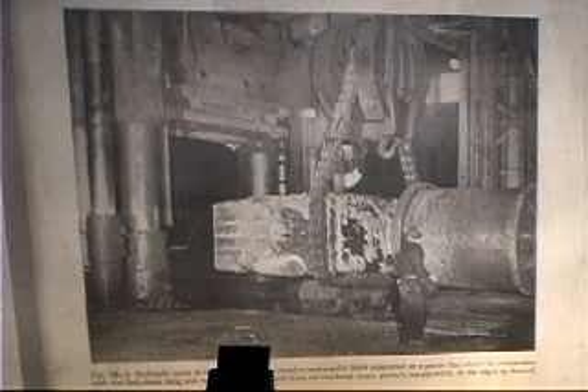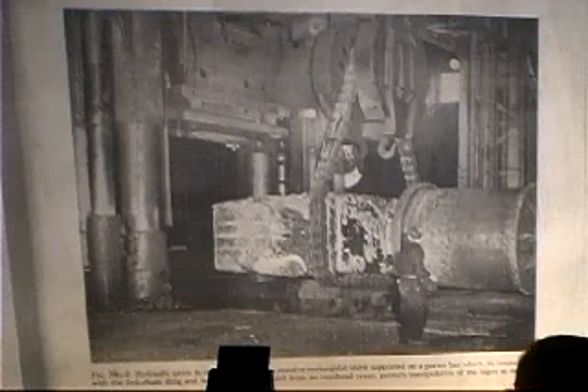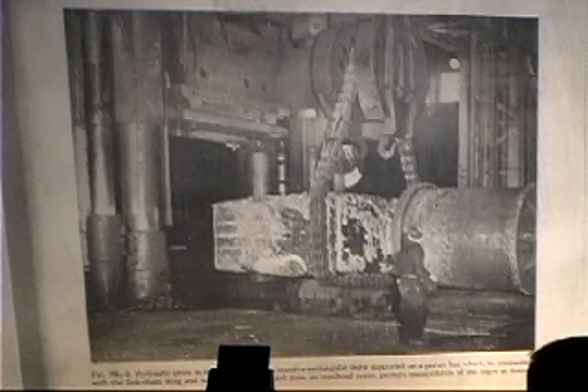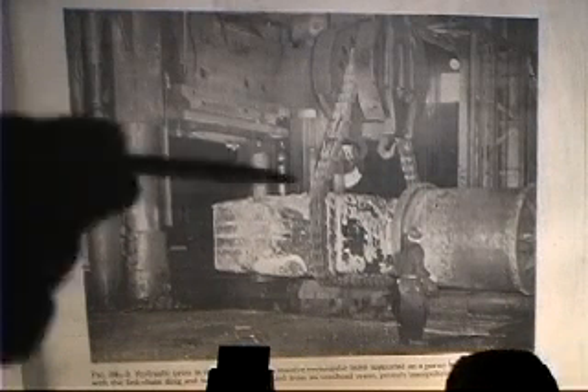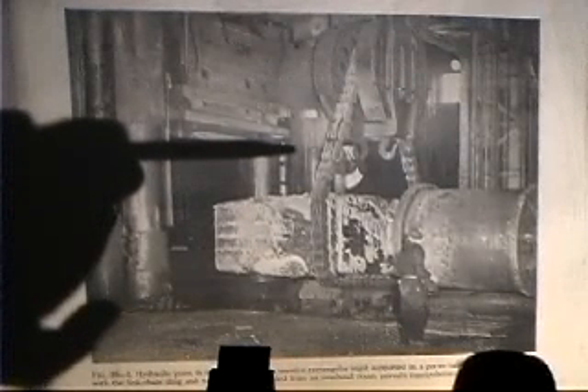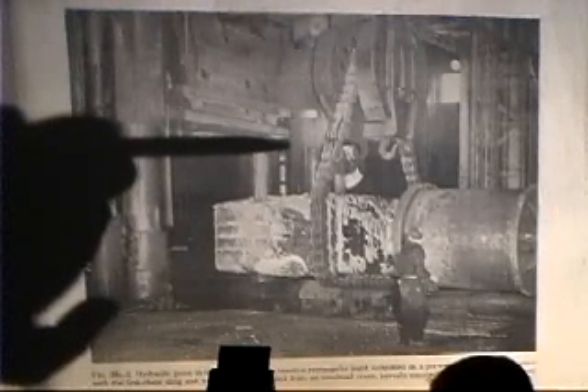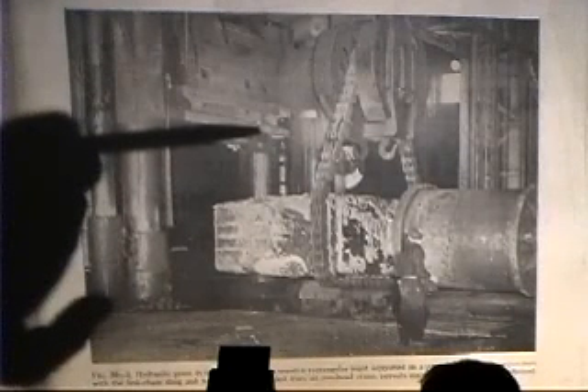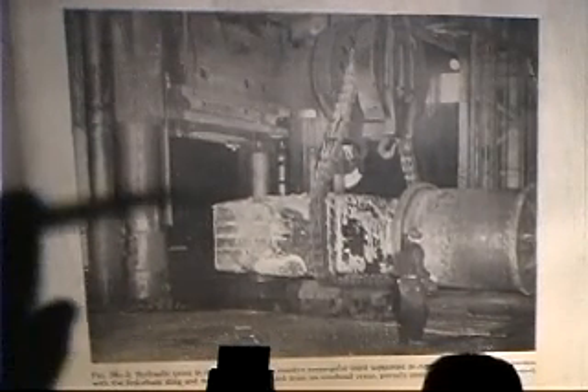I also remember when I went to a forging shop like that 27 years ago, first time. And this thing actually has to stay in the furnace for about a week to bring it up to temperature. It's so big to diffuse the heat all the way through. And now it's in the furnace, it's an air furnace, and you'll develop about an inch thick of oxide scale. It's just oxidizing in the furnace. And so when you forge it, the scale falls off.